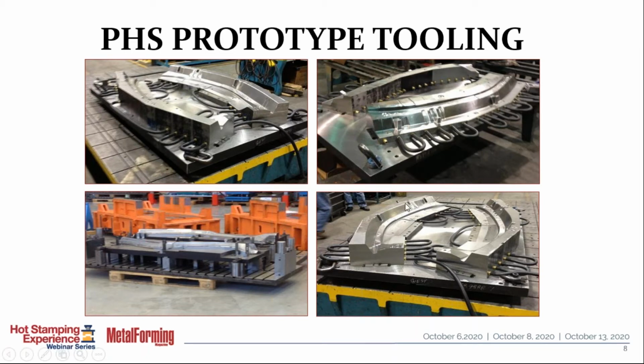Obviously, after you heat it up, if you try to put another part in there immediately, it's going to keep getting progressively warmer and warmer. So water cooling is primarily used to reduce the heat of the tool between cycles, to extract that heat from the tooling and get it into a water chiller where it can be removed and then replaced with cold water to cool the next cycle. In some cases, the part geometry or the thickness of the material or the cross-section of the tool may be such that you need to use the water to get proper part quenching during one cycle, but that's relatively uncommon.